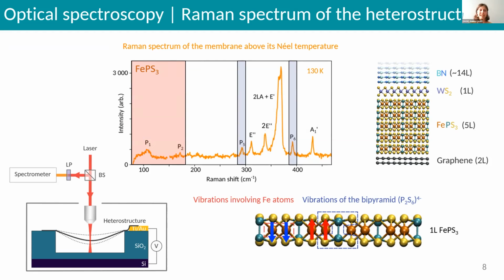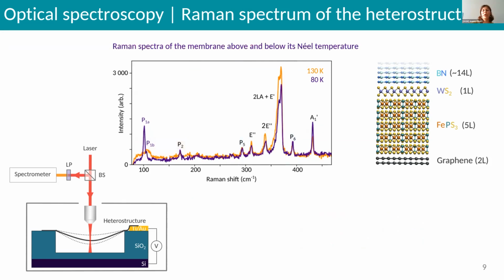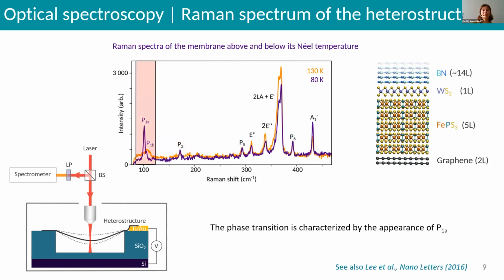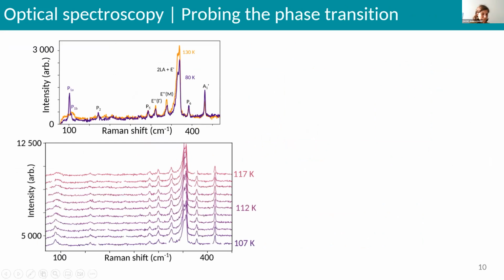Now, if we look at the spectrum below the phase transition temperature, we see that the striking element is the appearance of P1A, which will characterize our phase transition. If you plot all the spectra around the phase transition temperature, you can see that when the temperature decreases, you will have the appearance here, around 110 Kelvin, of this peak P1A.